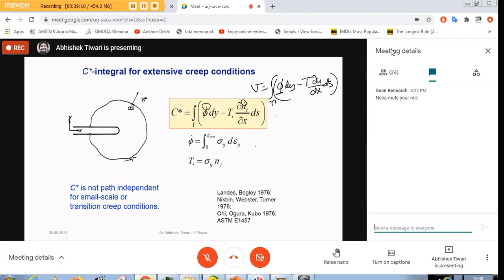Remember that this is not dJ by dt. It is not dJ by dt. So only those terms which are time dependent have been replaced with the rates of that. This idea works fine. It is also found that experimentally it works, but the philosophy is broken somewhere, because J defines the crack driving force at least for a stationary crack as long as we are loading it.